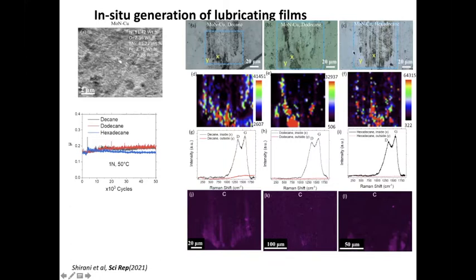So here you can see the wear track for the addition of decane, dodecane, hexadecane, whenever we're sliding across all the different environments. And now we also see similar behavior in different systems, such as oil, ethanol, methanol, kerosene, gasoline. So whatever hydrocarbon source we can get, it actually helps us to reduce significantly the wear of the systems and to constantly protect the surfaces. What is happening is that our surface reacts upon the sliding with the surrounding environment and reconstructs this carbon-based tribofilm, which allows us to significantly reduce the wear of the systems.